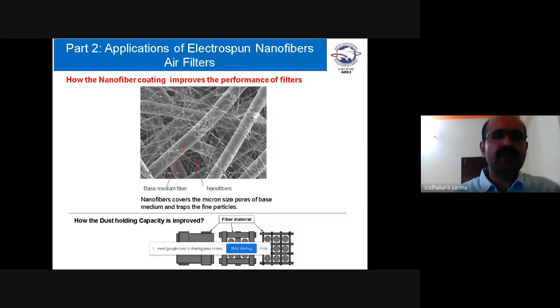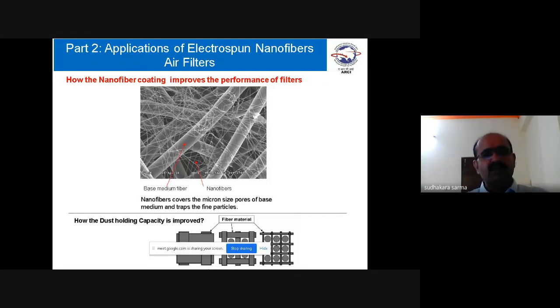Now I am explaining about the filter applications of electrospun nanofibers. One application is the air filters. What's the advantage of coating these nanofibers on air filtration medium? The advantage is it improves the filtration efficiency. How the filtration efficiency is improved: you can see the micron size fibers of the filtration medium. On that, if we coat the nanofibers, the small fibers cover the micron size pores of the base medium and trap the fine particles. So with that we can increase the filtration efficiency.